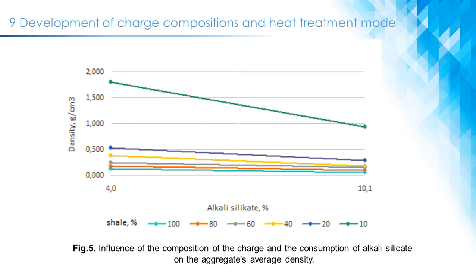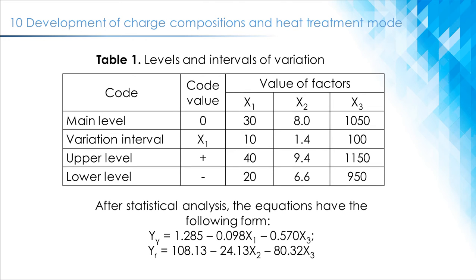Intense and excessive release of gaseous products does not improve the porization process but causes the formation of large interconnected pores, passing into cavities and open pores. Since previous studies have established that the most suitable for obtaining a porous aggregate is a crude mixture consisting of crushed sludge, crushed shale, and water glass, these mixtures have been used to study the influence of technological factors on the properties of the porous aggregate.